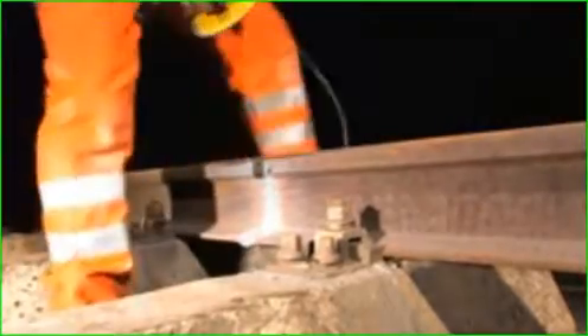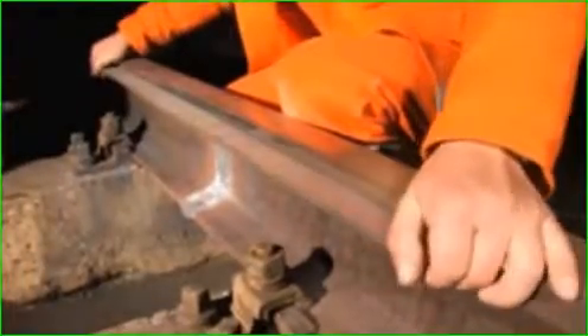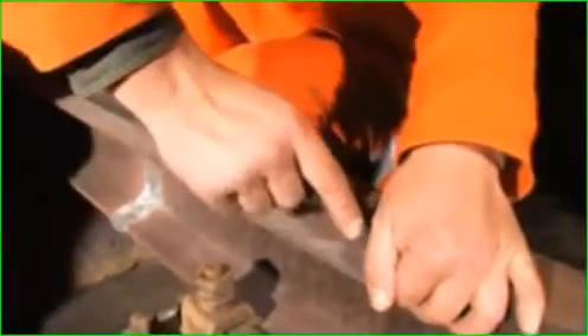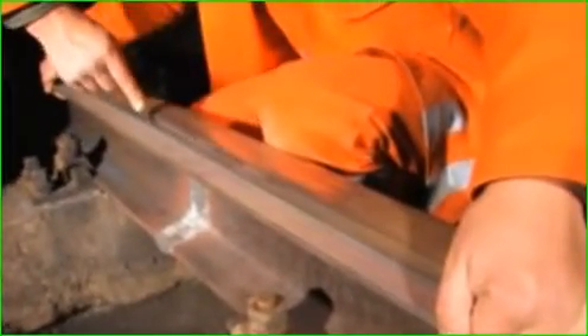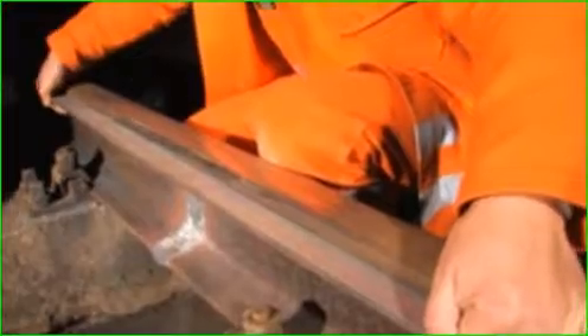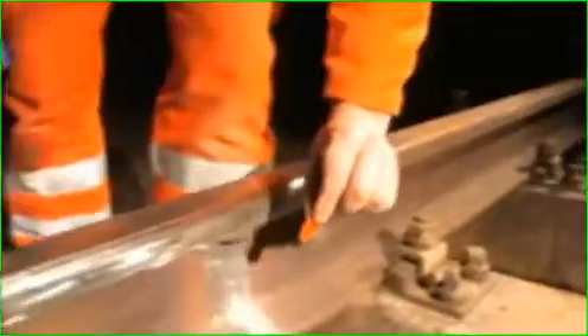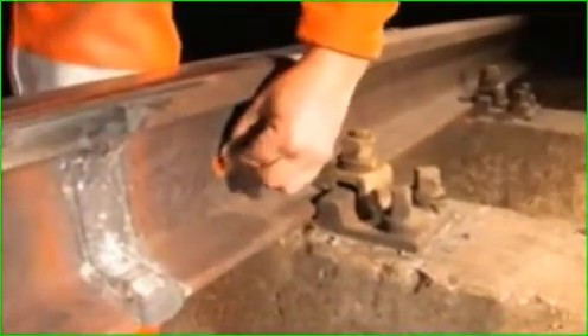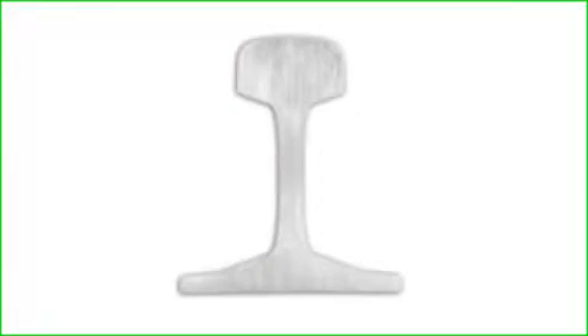By means of fine grinding, the rail head profile at the running surface, at the head radius, and at the running flank is to be restored. The compliance with the demanded tolerance is normally checked by the 1 meter straight edge and by the feeler gauges at the running flank and at the running surface. The weld is to be marked. And this way, a complete thermit weld looks at a Vignole rail, at a grooved rail, or at a crane rail.